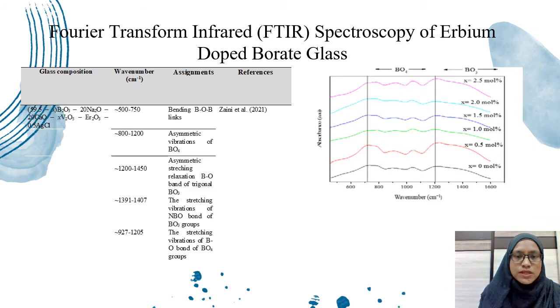By Zaini et al. 2021, between 500 until 750, the bending of BOB links; at 800 to 1200, the asymmetric vibration of the BO4; at 1200 until 1450, the asymmetric stretching relaxation of the BO band of trigonal BO3; at 1391 until 1407, the stretching vibration of NBO bonds of BO3 groups; and between 927 until 1205, the stretching vibration of BO bonds of BO4 groups.